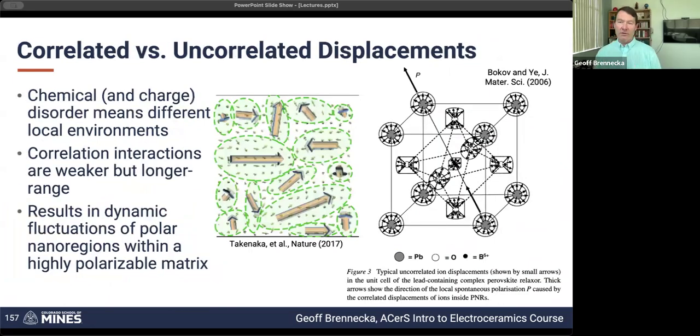So what it boils down to is the fact that those dipoles that I was talking about, the atoms being shifted apart from exactly where they want to be in the lowest energy point because of thermal vibrations, they're going to be wiggling all over the place. That happens in every material. But in well-behaved standard ferroelectrics, those displacements are coordinated. And so the titaniums all sort of shift together, the bariums all sort of shift together, and the oxygen sublattice shifts as well.